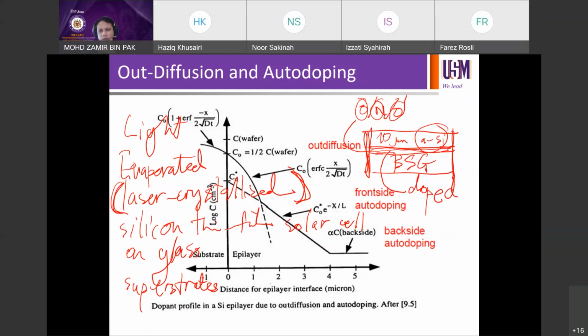oxide, nitride oxide. You can dope them before your silicon. Maksudnya saya start dengan glass, kemudian saya deposit interlayer yang oxide, nitride, oxide, kemudian saya evaporate amorphous silicon. So proses dia mula di bawah. Start off with bare glass, tak ada apa, cuci. Oxide, nitride, oxide, amorphous silicon. The amorphous silicon is not doped, maknanya the intrinsic silicon, but your oxide, nitride oxide can be doped beforehand.